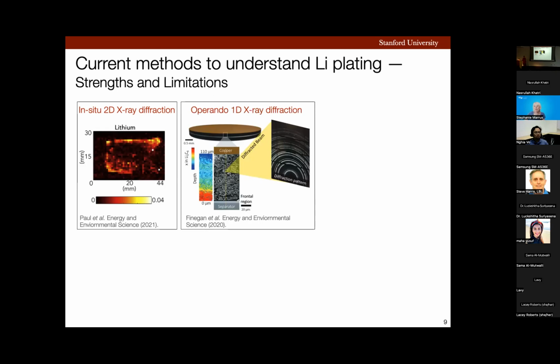Second study was led by scientists at NREL who employed operando X-ray diffraction to investigate spatial dynamics of lithium plating. Their data showed that spatial heterogeneities of lithium plating also span as a function of depth of the graphite electrode, which is great. However, this study is limited to 1D.